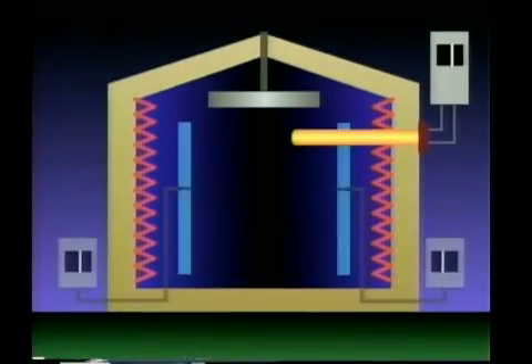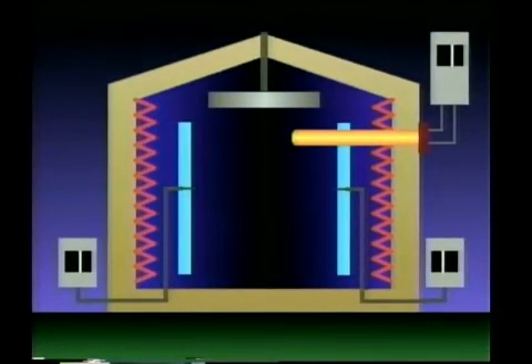Problems of radiation heat treating usually come from an improper furnace design or damage to the furnace which has not been corrected by proper maintenance procedures. The radiation survey is usually accomplished by placing panels on a rack at the extremities of the work zone and attaching a thermocouple to each panel. The panels usually measure 1 foot square and are approximately 1/8 of an inch thick.